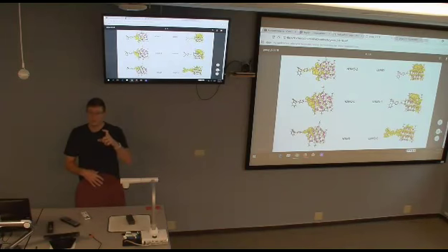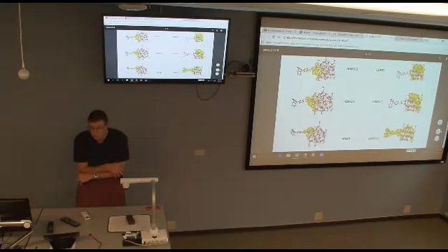Yeah, so she had something a little over 3 for her quantum dot, and then the addition of both of these organic linkers were about 1.58 and 1.59, so very similar in terms of just separating out the energy states. But putting something like that together, if it's going to hybridize, it's going to lessen the energy for some type of excitation. But you probably expect that it will be stabilized if they are becoming hybridized. Your charge transfer states probably will stabilize your HOMO, meaning you're pushing it down.